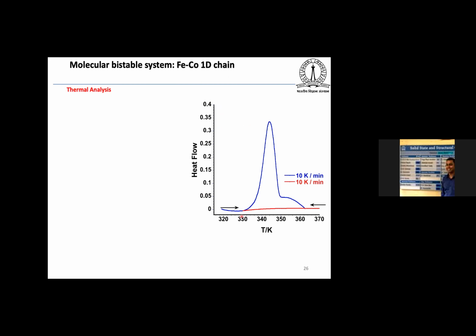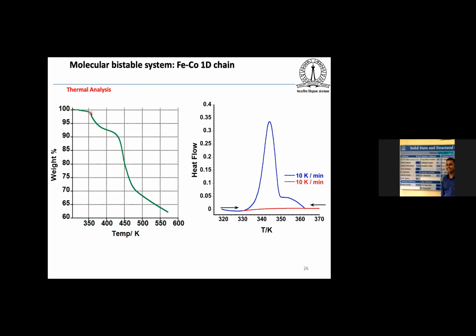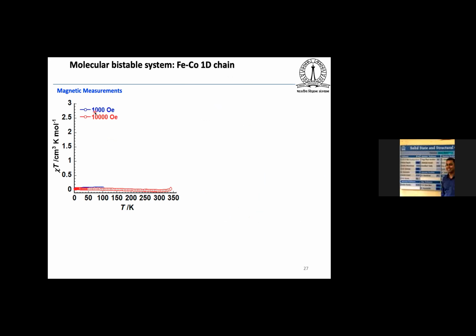And you can see here, when you look at the DSC data, there is a nice peak at roughly around 345 Kelvin. That is also suggesting that there is electron transfer or a first-order phase transition going on in the system. And you can see the system is almost up to 350 Kelvin. And then what we have observed in the χT versus T plot, when we heat the system above 350 Kelvin, there is a sharp increase in the χT value. That is also suggesting that metal to metal electron transfer is happening at high temperature.